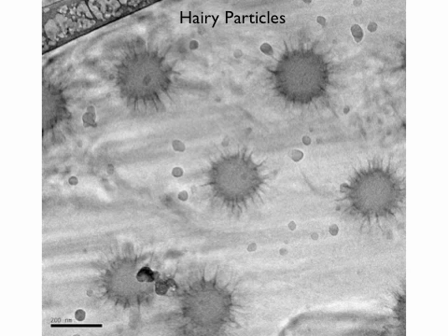And this is almost like what I want to call the wet hair effect. Because the ice crystallizes, it pushes the polymer chains together. So you see a bundle, like you have with wet hair. You have a bundle of them, and because it's a bundle, you can see them. If they're all nicely dispersed, you won't be able to see them, but in that particular case, you will be able to see them. So here you see clearly the core, and you can roughly guess how big this hairy layer is.